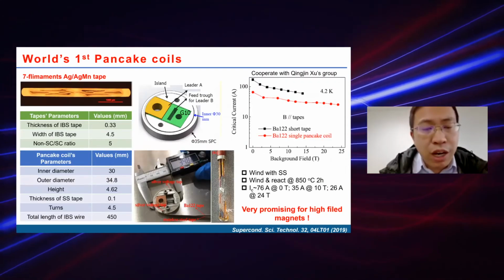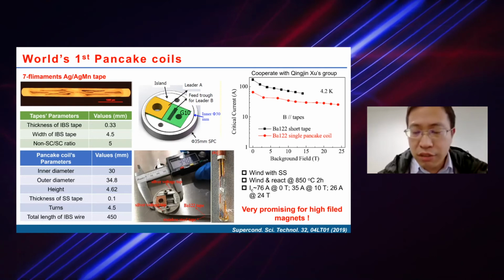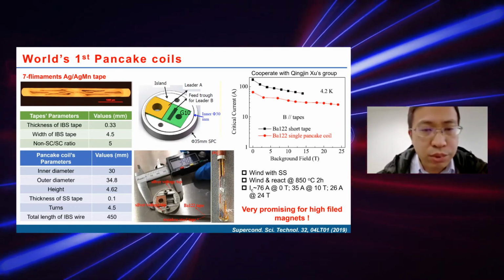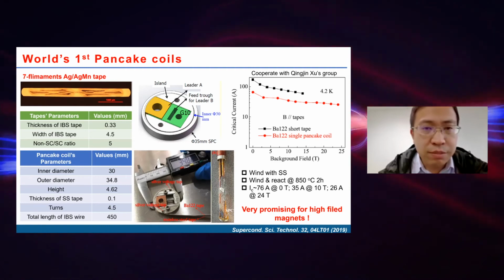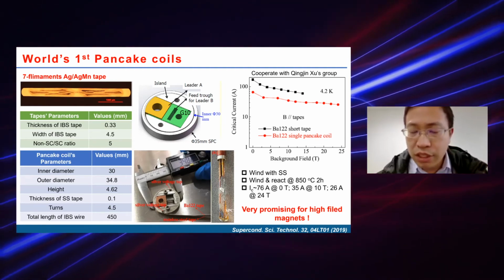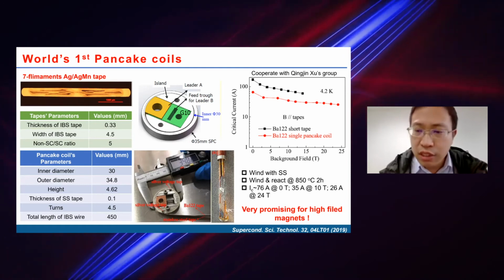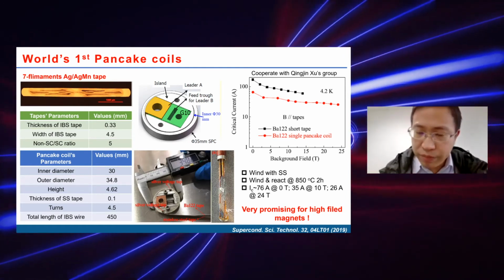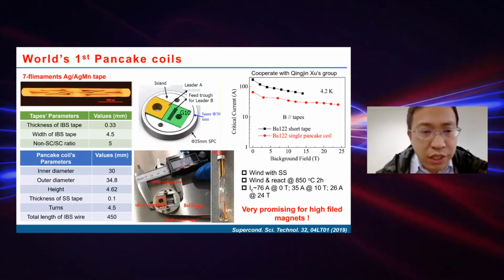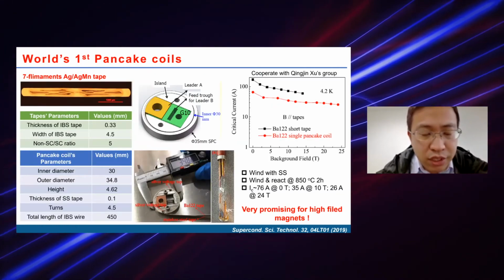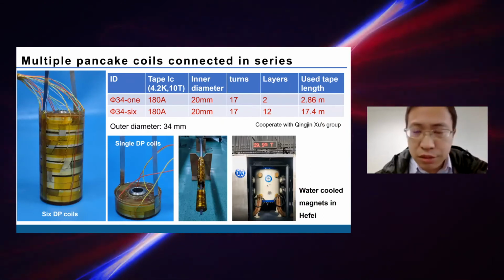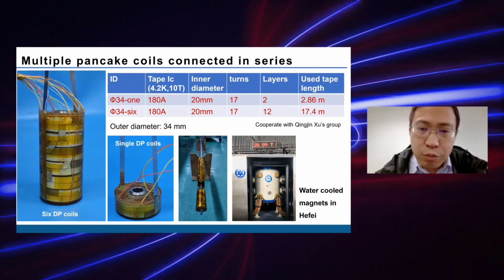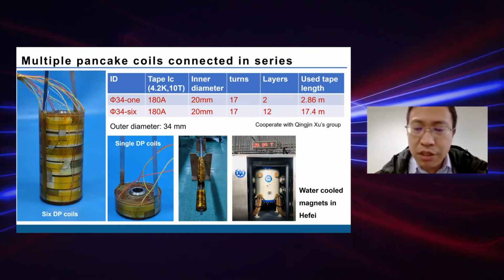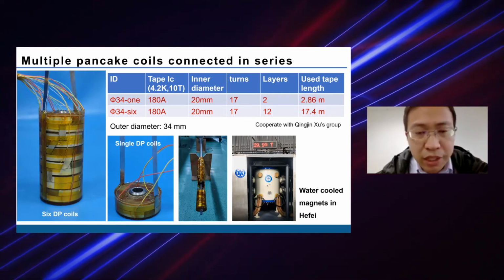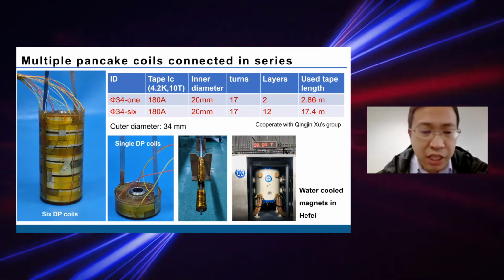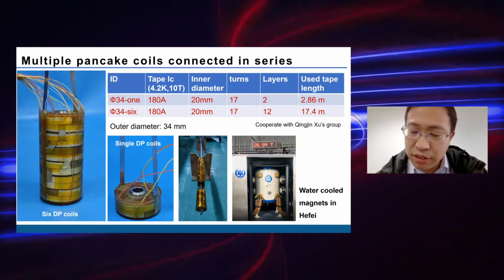Based on our 100 meter long tapes, we cooperated with Qingjin Xu's group to fabricate the world's first pancake coils. And we can get a very good performance at 24 Tesla. Here the inner diameter is actually 30 millimeters, and we continue to decrease the inner diameter below 20 millimeter to fabricate the single double pancake coils and the 6 double pancake coils, and test them in the water-cooled magnets